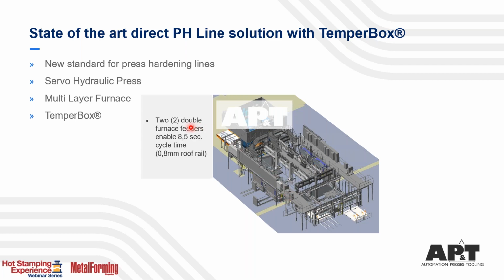In total, we have what we call furnace feeders. Those are the feeders that feed the cold material into the furnaces and also the hot material from the austenitization chambers into the temper box and out of that into either the centering table or directly into the press, into the forming die. If we run monolithic parts, and that's the nice thing with this press hardening line, we can run either the temper box process or we can run conventional press hardening where you create monolithic parts. If we run monolithic parts for a 0.8 millimeter roof rail and those 4 furnace feeders in total with 20 austenitization cavities, we do reach a cycle time of 8.5 seconds.